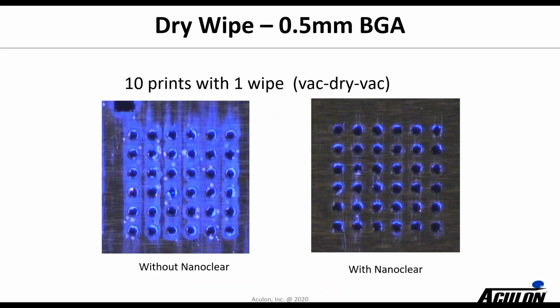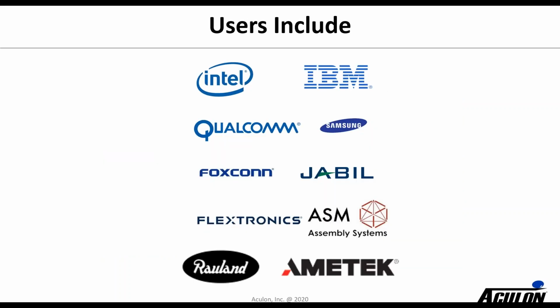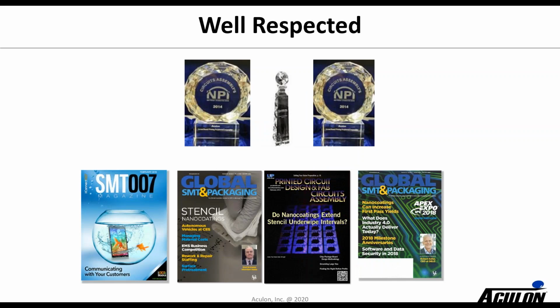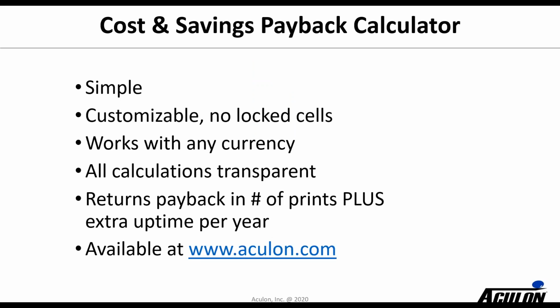To try to physically demonstrate what's going on, you'll see we added a UV tracer into the flux, and you can see without NanoClear, it's being smeared around the bottom side of the stencil quite significantly, and a lot of it there. Whereas with NanoClear on the right-hand side, you can see very little flux is getting transferred. So you're getting cleaner, better prints, and in this case, this was 10 prints to a 1 wipe cycle. This technology we've had in the marketplace for a number of years, and we've got many significant and sizable users out there that demonstrate and use this technology. It's been well respected. It's won numerous awards. It's had numerous cover stories written about it, and it's very efficient from a cost standpoint.